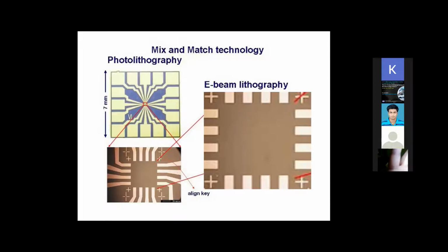Now what we do after we make the photolithography, we deposit gold and do lift off, and ultimately what we get is like this. So this contrast actually showing gold on silicon or maybe silicon dioxide, and having these cross marks. Now we make some nanowires. Whatever nanowire we make, we dissolve this nanowire in a liquid, then drop cast the nanowires over this. So nanowire will fall irregularly on all the regions.